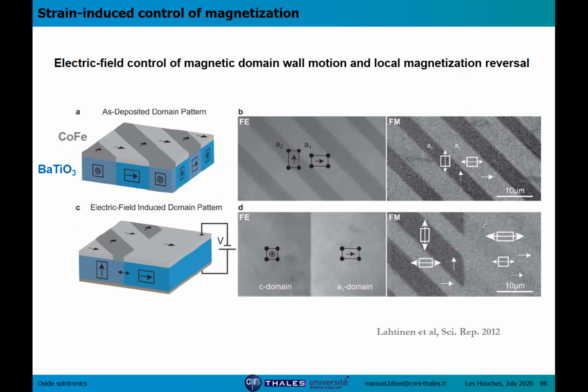Continuing with this strain effect, this can also be visualized using magneto-optical Kerr effect. This is work from Sebastian van Dijken, cobalt iron on top of barium titanate. Barium titanate is a ferroelastic, and at room temperature, the polarization can be oriented along two in-plane directions or out of plane. Typically in the virgin state, it's going to be mostly along the in-plane. So you have these so-called A1 and A2 coexisting domains. This is an optical image using a polarized microscope, and through the birefringence of barium titanate, you can image the domains. And you see that when the cobalt iron